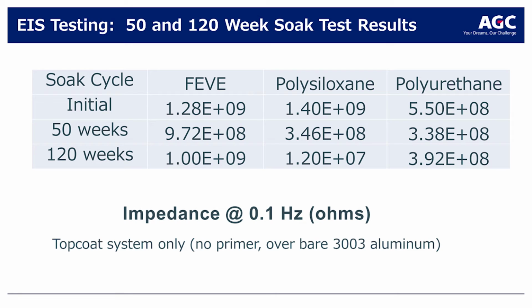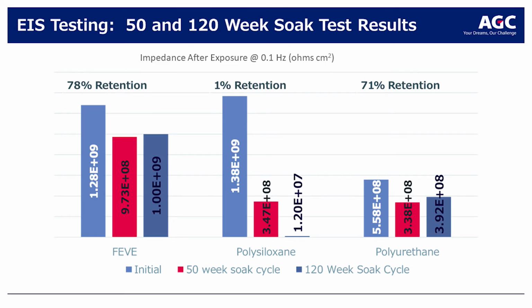You can see here that all initially were good. All are over that 10 to the 8th after 50 weeks, but after 120 weeks, the polysiloxane falls below that. Again, interesting results for us. This is kind of graphically looking at the same thing, looking at retention of impedance, or how little the impedance changes over time. And you can see here it's a little bit easier to see the change in impedance over time. And again, the urethane, since it's over 10 to the 8th, it does have good corrosion resistance.